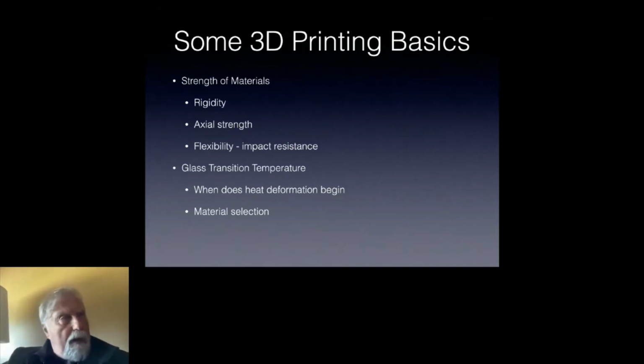One of the insights that I discovered in my research, and getting myself less stupid about this, was that for many of our easily accessible materials, the glass transition temperature is about the same as the glass transition temperature of the epoxy resin we use in our fiberglass and carbon fiber composites, which means that we can use these advanced plastics in many of the same places, modulo strength, that we can use fiberglass and carbon fiber. And last, there are some fascinating things we can do with tuning the slicing parameters. I'll talk about slicing a bit later.